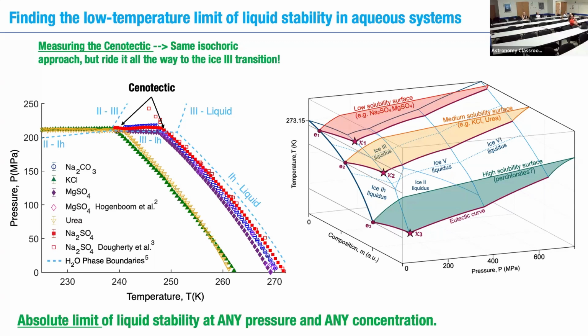So, in these initial data sets, it sort of jumped out to us that we can formalize or contextualize the cenotectic concept a little more richly by thinking about different relative molar solubilities of different salts. You can see we show a low solubility surface up here that corresponds to this group, and a middling solubility surface that's right here. And then you can imagine that, as you go to higher and higher solubilities that have lower and lower atmospheric pressure eutectic temperatures, you'll actually cross this boundary here, where the denser phase that you run into over here, instead of being ice 3, like it is for these guys, will end up being ice 2.